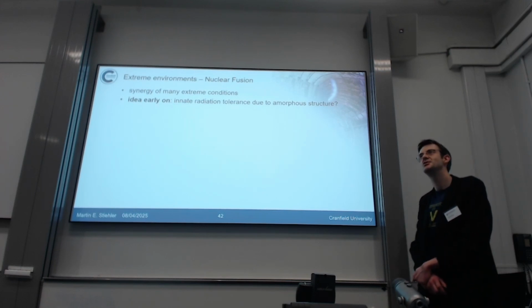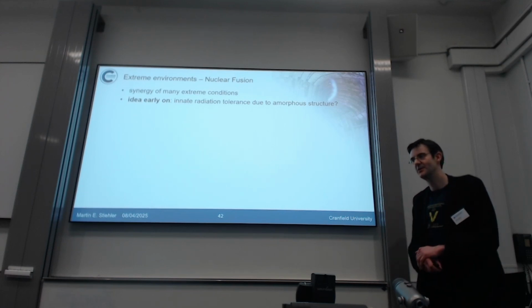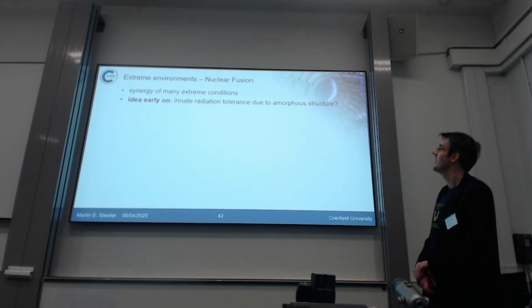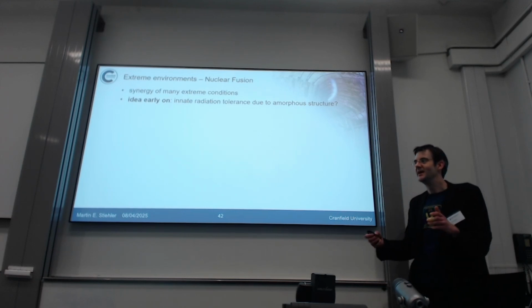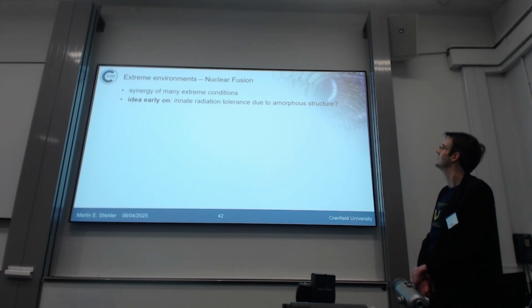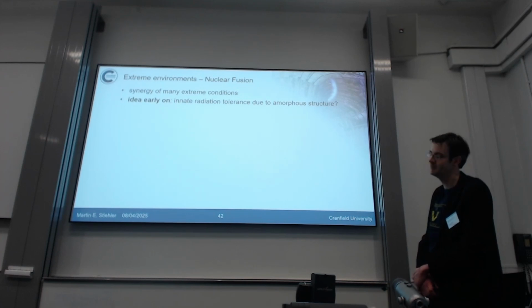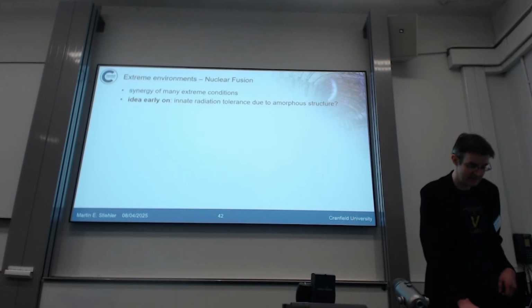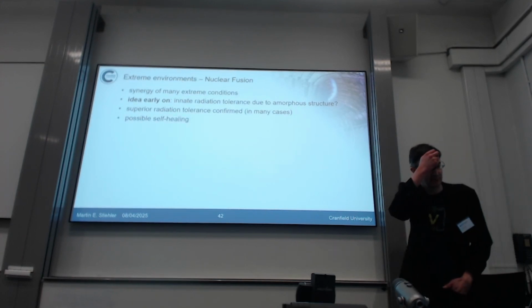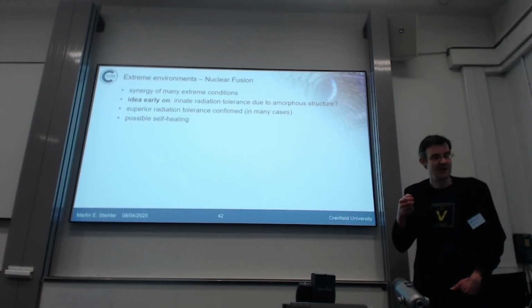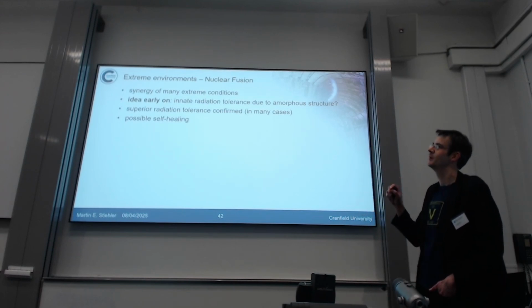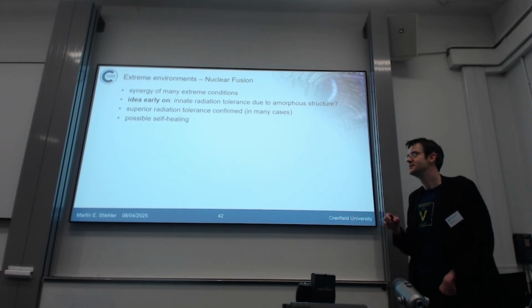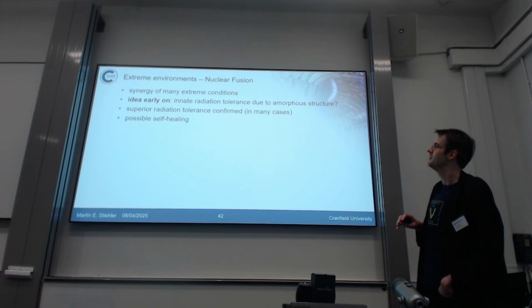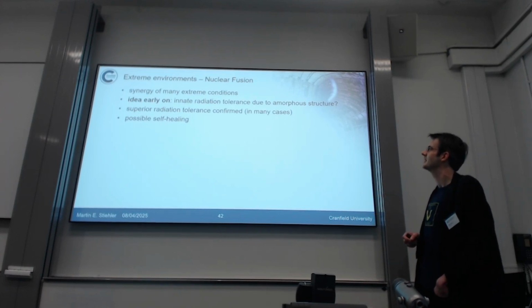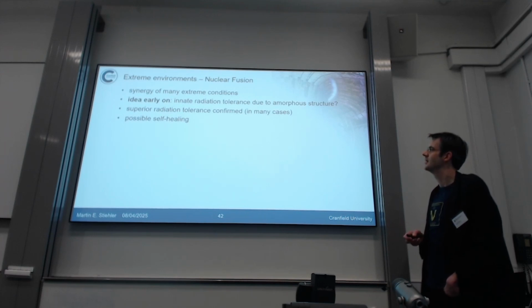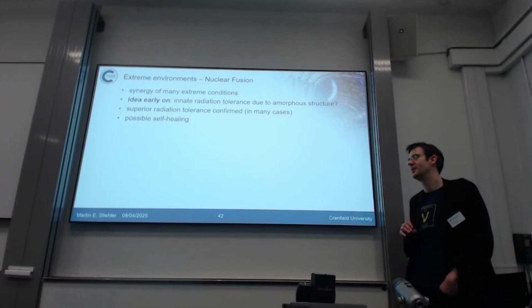Usually you think about neutrons disturbing or destroying the crystalline structure, turning the material into an amorphous material, but when you directly start with an amorphous material, that may give the material a high resistance against irradiation damage. And that was actually confirmed in many cases. In the beginning, when the idea was floated, there were not really bulk metallic glasses available, so the interest, I think, ceased a little bit, but it is growing now that we have bulk metallic glasses, and there are also reports of possible self-healing of defects introduced by the radiation.